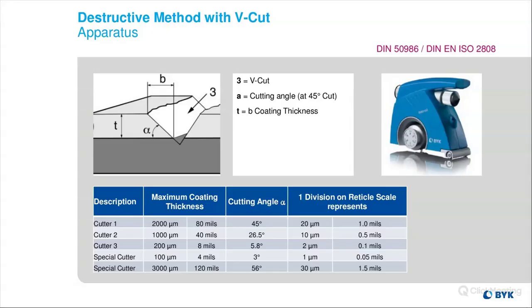These cutters are based on standards, which say that if your coating is between this thickness, or we have the example here on the screen actually, for cutter number 1, if your maximum thickness is 2,000 microns or 80 mils, then you use that one. And you use cutter 2 if it's less than 1,000 microns, cutter 3 if it's less than 200 microns. And what we see is that they each coincide with an angle, and that angle is used in the calculation to determine the true coating thickness when we look through the microscope.